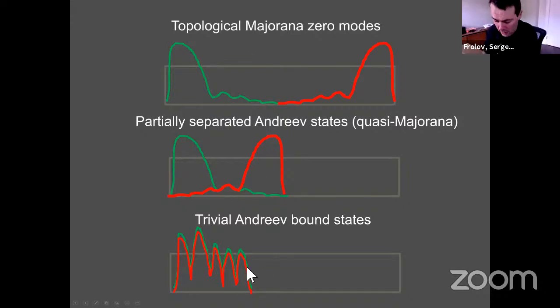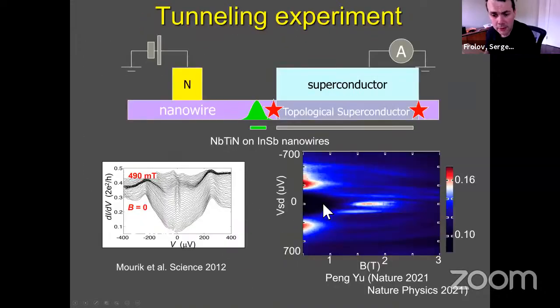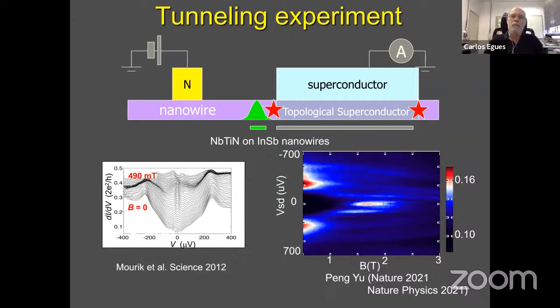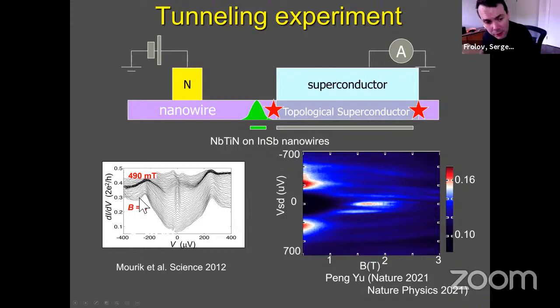Okay, yes, that's great. Let me first show you this data again. This data with soft gap. Because maybe not everybody knows what we're talking about, let's look at the graph on the left. This original data at zero magnetic field without any Majorana possibility. We have this shape, 2 spikes and a suppression in the middle. The 2 spikes are well known. It's BCS peaks in the density of states created by expelling states due to superconductivity from the middle of the gap around Fermi level to higher energies.